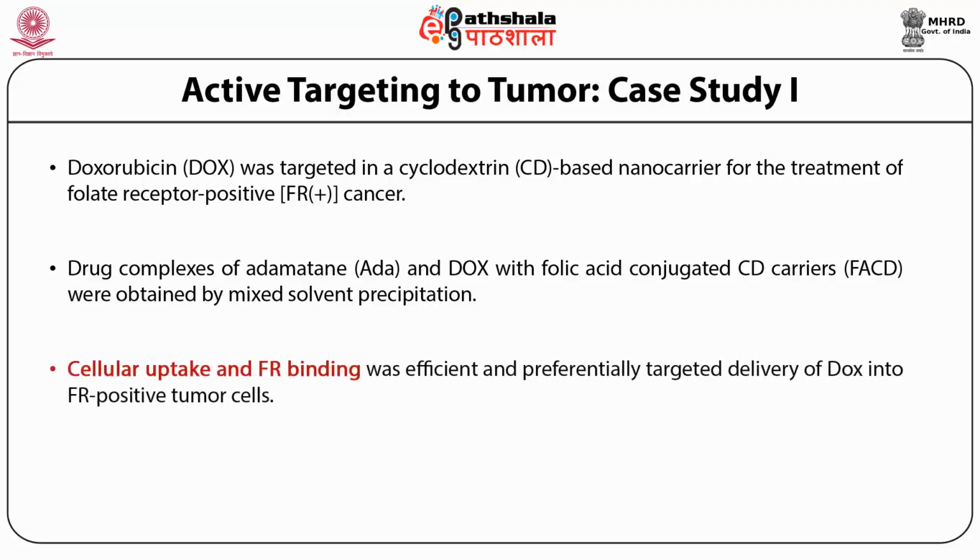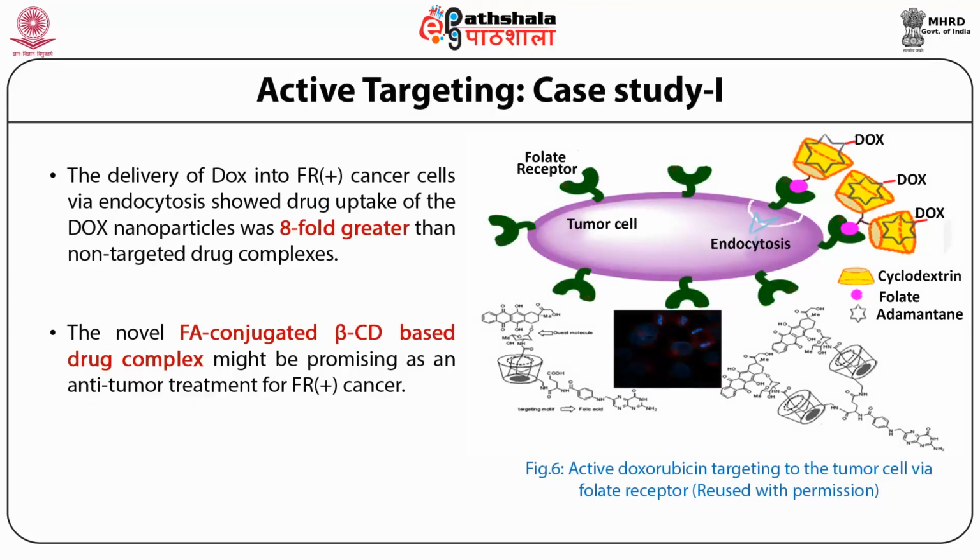It was observed that the drug was delivered to the cancer cells specifically rather than to non-cancerous tissue, and the targeting of the drug was found to be 8-fold increased at the specific target site via receptor mediated endocytosis. So this study showed a promising case of active drug targeting via the ligand receptor mechanism, as shown in this figure.